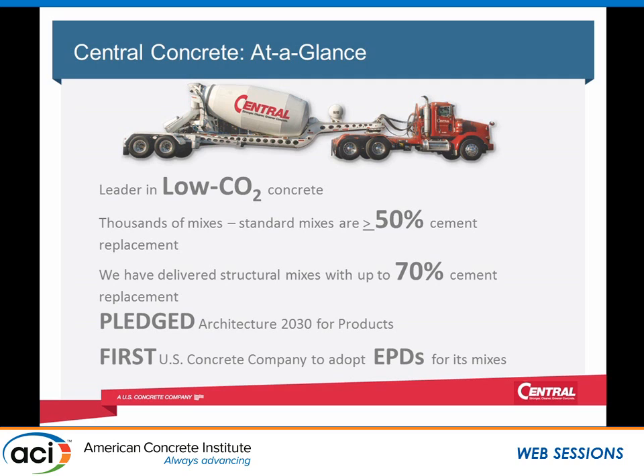Our standard mix that we put out the door every single day is 50% cement, 30% slag, 20% fly ash. That's our standard mix. If I had my laptop, I could bring up the order snapshot for the day. When I looked this morning, we had about 4,000 yards that we were doing, and I would say about half of that is with this 50% SCM mix. It's very common for us to use it.